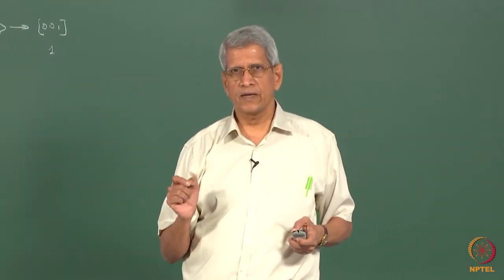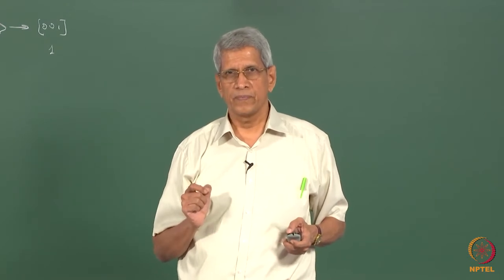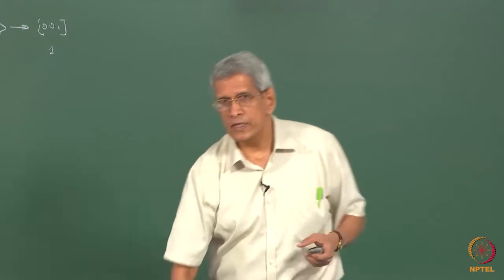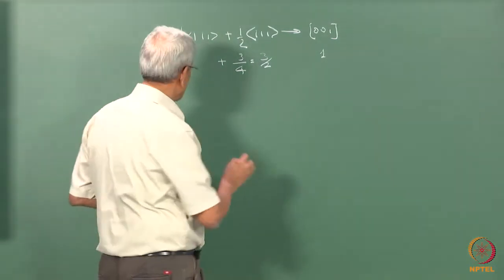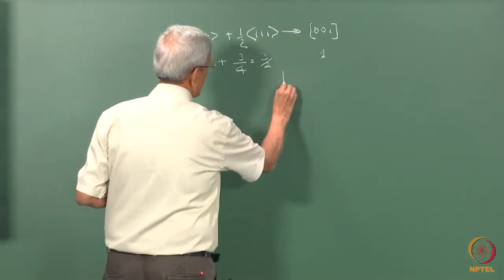Correct? What has been observed is that when this dislocation has got an edge configuration, for an edge dislocation, we look at it like this. This is where the tensile stress is going to be there. The compressive stress is going to be there in these directions. When the Burgers vector is large, it has been observed that under tensile loading, these regions act as nucleation for crack to develop.